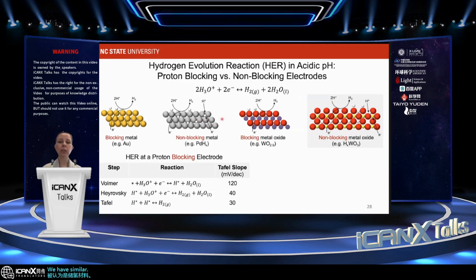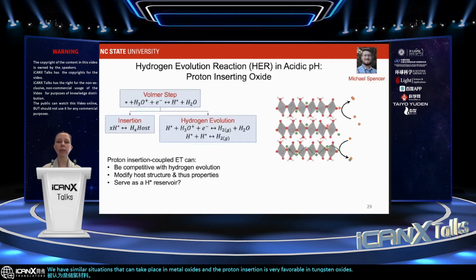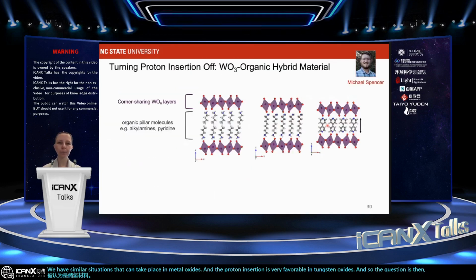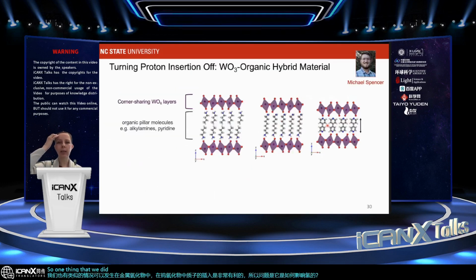We have similar situations that can take place in metal oxides, and the proton insertion is very favorable in tungsten oxides. And so the question is then, how does it affect the hydrogen evolution reaction? So one thing that we did early on is we said, well, what happens if we turn the proton insertion off? And we can do that by basically modifying the structure of the material.